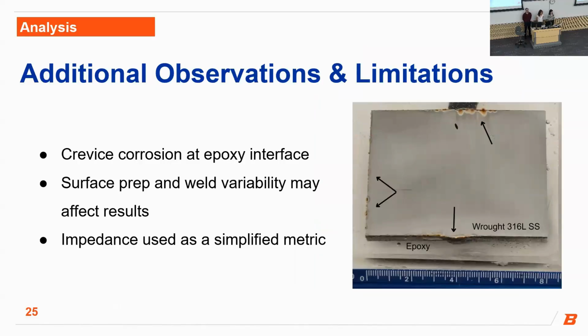There are a few observations and limitations worth noting. We observe crevice corrosion at the epoxy interface of many of our samples, as you can see in this picture, and this may have influenced the measured impedance responses. Variations in surface preparation and weld variability could likely contribute to differences in the passive film forming between samples, and it's important to note that impedance is a simplified metric and does not capture all aspects of corrosion mechanisms.